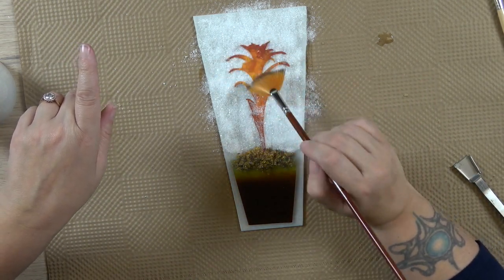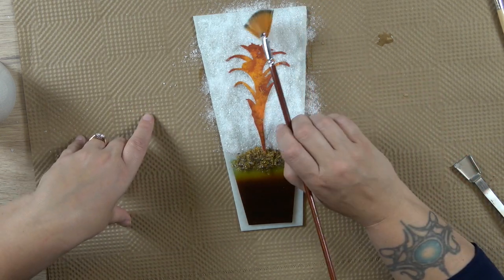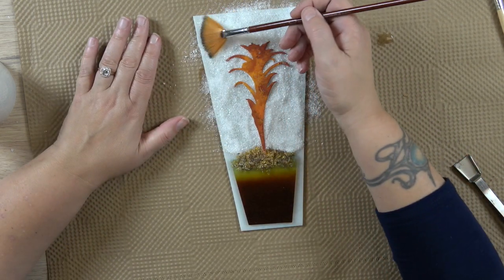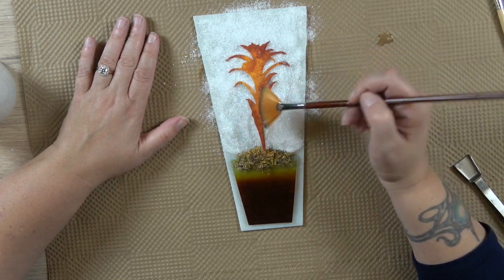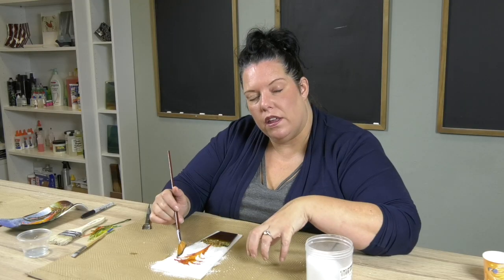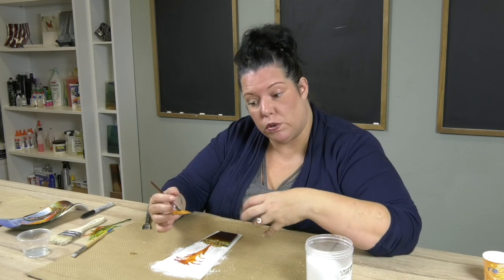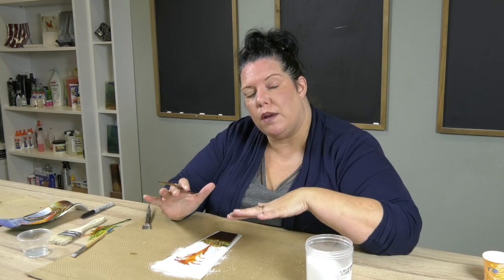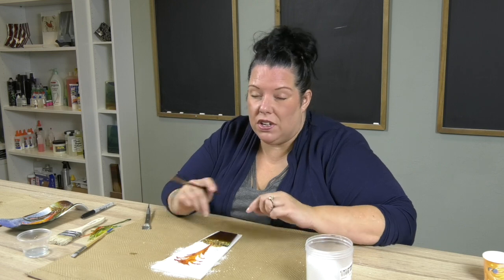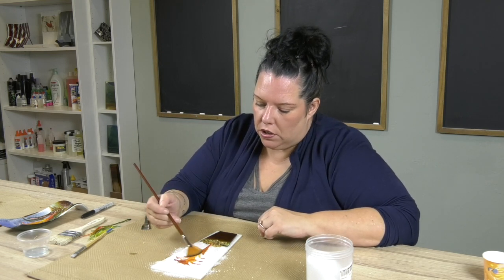And it's not because you're going to color wash everything, but we definitely want to have as even a thickness as we can, because that can cause us some problems in a slump otherwise, all right? Because if you have very thin areas and very thick areas, guys, the areas that are heated up first, which are the thinnest areas, when you go to slump, those will soften up first and the rest will not be ready to slump. And that's when usually a lot of splits and cracks happen in the slump. If you ever had a split or a tear, that's the reason why. So look at that, perfect, beautiful, love it.